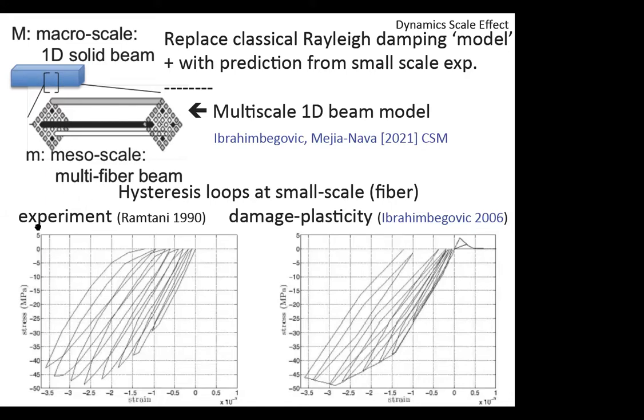So basically, you have your experimental measurement. A typical concrete compression test in dynamics would be this. You can see that concrete has both a change of the elastic response, that means you need something like damage, and you need a residual deformation, which is typically brought by plasticity. So we matched this with a coupled damage plasticity model in a paper which came out this year in Coupled Systems Mechanics with Rosa della Mea Nava, a postdoc of mine now.